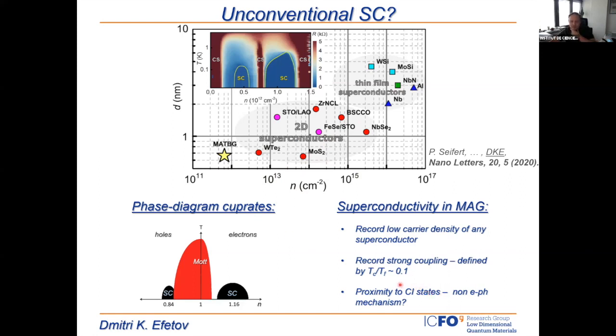Tc is still really sizable. I think the highest Tc we observed so far was 5 Kelvin. And if one looks at the ratio of Tc to the Fermi temperature, it's extremely high, and only comparable to cuprate superconductors. It's orders of magnitude larger than conventional superconductors like aluminum or niobium. And of course, last but not least, what caught a lot of attention is the phase diagram, which naively looks very similar to the cuprates, where again we observe superconducting domes upon doping of correlated insulator phases.